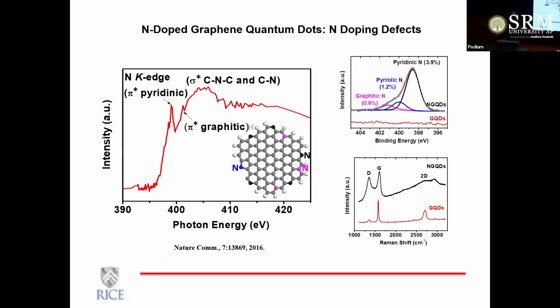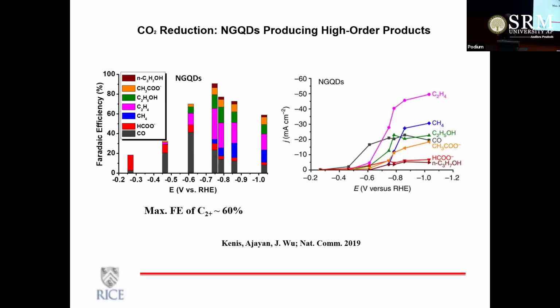Now, nitrogen-doped carbons are very important. Huge amounts of work have gone in by many groups around the world to see if you can replace traditional catalysts like platinum, which is expensive and rare, with carbon nitrides. Platinum is used as a catalyst for many applications, and it's not an easy material, and it's expensive. So carbon-based catalysts have become very popular. We have been playing around with nitrogen doping, single nitrogen atoms in carbon. It's complicated, depending on the exact positions that nitrogen takes in these graphene lattices, but nevertheless, you can get catalytic activity from these.